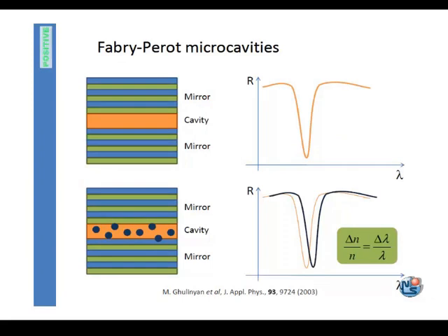Up to now, porous silicon was investigated mainly because of the possibility to make these nanocavities. That means that you etch two mirrors, and in between you put a defect layer. If you look at the response of this structure, you will see a very high reflectivity band with a dip in the middle because of the presence of the defect layer. Now, if you want to build a sensor on this type of structure, the idea is that if something enters your device, the refractive index will be affected, and this is translated into an optical shift of the cavity peaks. That means the more things enter your sensor, the greater the optical shift will be.